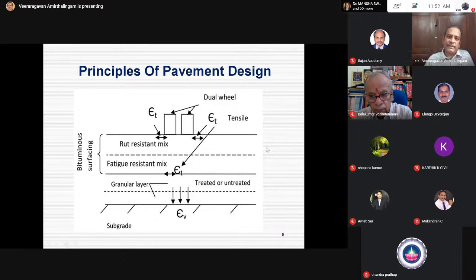My principle is that this is a critical factor that has to be considered, which is the fatigue at the bottom of the bituminous mix. Again, there are two different layers in the bituminous at the top of a pavement. One is the wearing course, which is a rut resisting mix. The second is a bottom layer, which is the fatigue resisting layer. So the bottom layer should resist the fatigue. The top layer should resist the rutting, even though both are called bituminous layers. So the design philosophy for the two different layers are different. Don't say bituminous concrete I provide or HMA, hot mix asphalt, I provide, it will take care of both. No, you have to design them separately.